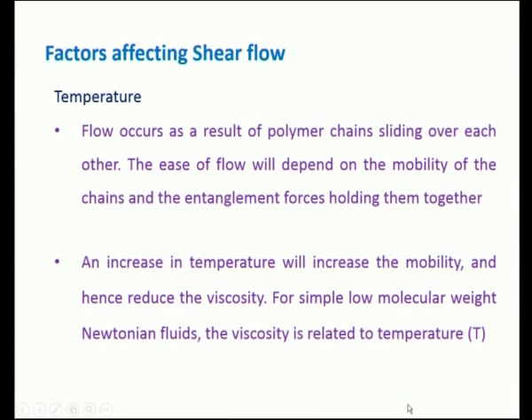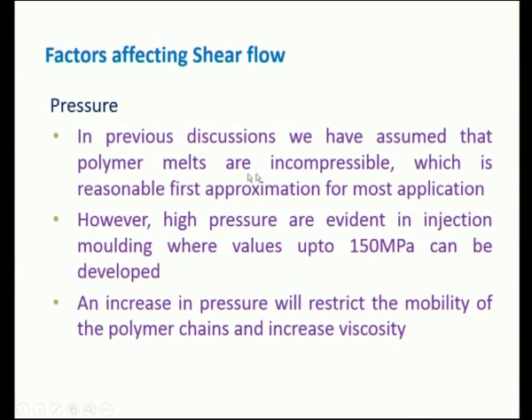Next, pressure. In all these discussions so far, we have assumed that polymer melts are incompressible. That means there is no effect due to pressure, which is a normal or a reasonable approximation for most of the applications. However, there is some evidence with respect to injection molding where high pressure values are possible, even up to 150 megapascal pressure is developed in a typical injection molding process.